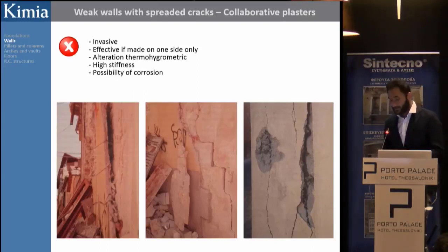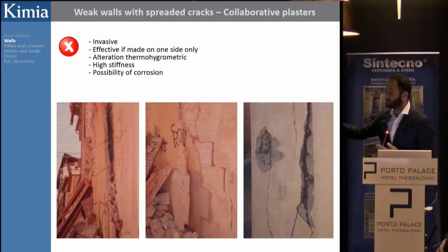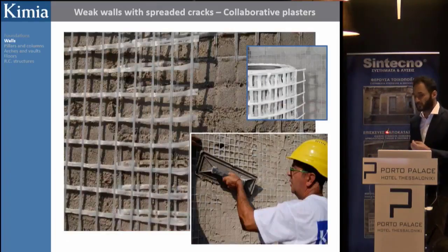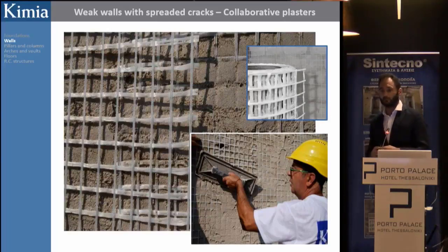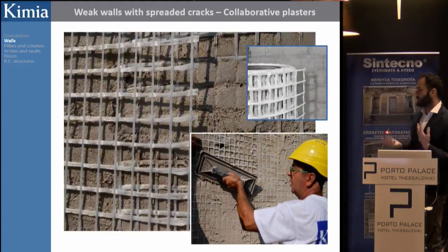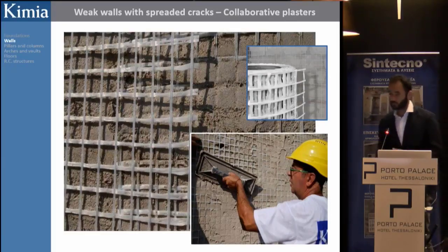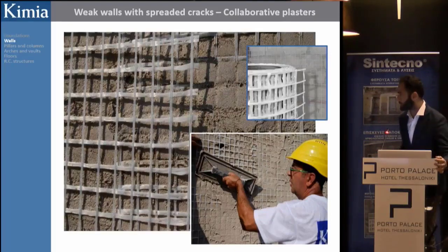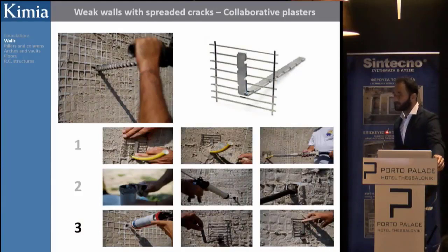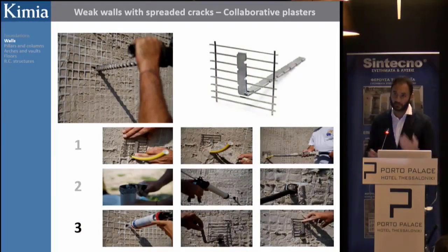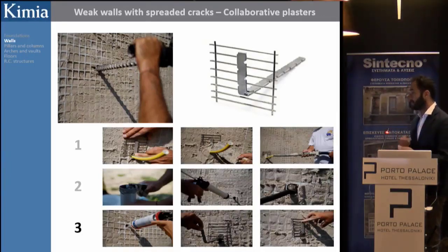And in any case, some problems will arise because the steel meshes will in time tend to corrode. So nowadays we are developing some second generation collaborative plasters based on the use of alkali-resistant glass fibers. So we have no problem with corrosion as happened with previous collaborative plasters, applied with natural hydraulic lime-based mortars. So we overcome the problems dealing with chemical compatibility, stiffness, etc. that we have been discussing so far with cement-based plasters. This is a system we are now testing and certifying also in terms of design, procedure, certification of systems. Italy is moving in this direction.